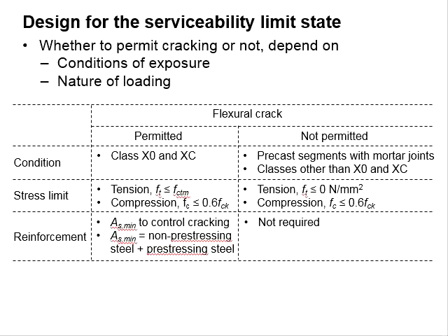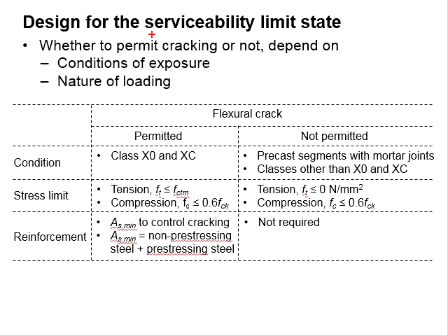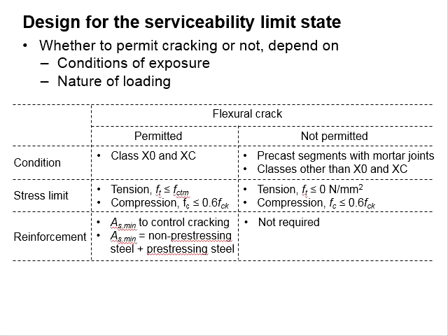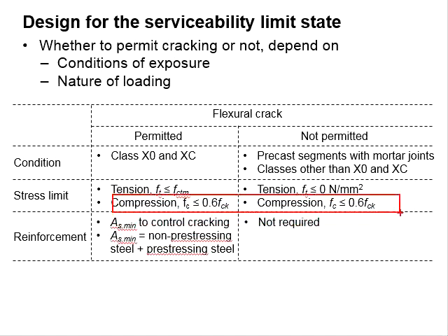A prestressed member may or may not be permitted to crack. Whether cracking is permitted depends on the conditions of exposure and the nature of loading. The cracking here refers to flexural cracking. Concrete of exposure class X0 and XC is allowed for flexural cracking. Other than these classes, the concrete is not allowed to undergo any flexural crack, or in the case that the concrete segment requires mortar joints, cracking is not allowed.